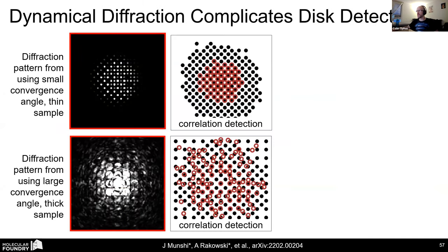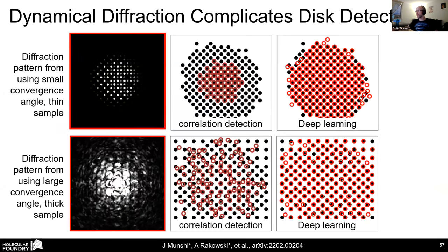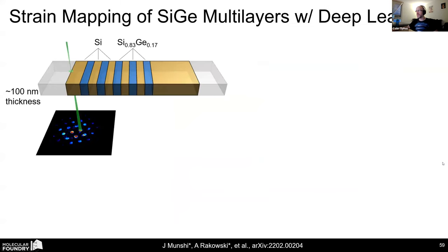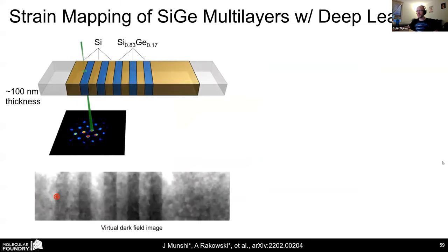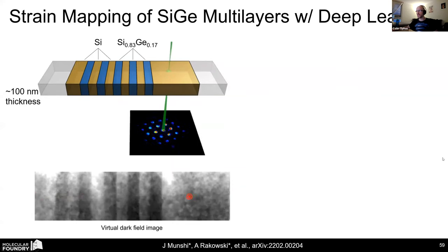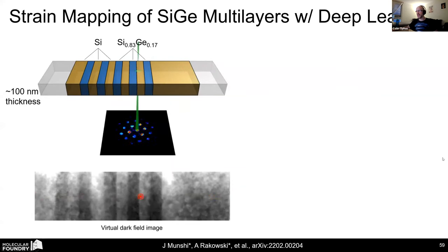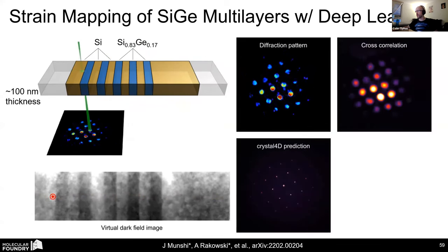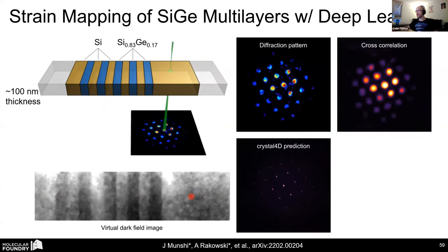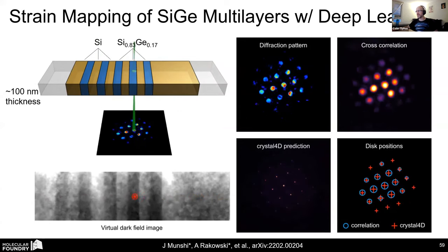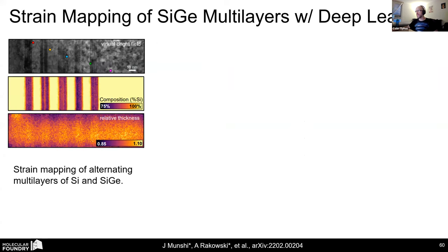And so if I return to those two simulated examples, you can see that the deep learning network just has no problem whatsoever. And a part of this is because it has seen every single crystal structure that is known essentially from these databases. So we can encode a huge amount of prior knowledge into these networks. So I'll show you one experimental example, 100 nanometers thick of silicon and silicon germanium multilayer stack. And if we do our 4D STEM scan, and then we use correlation or the machine learning method to measure the displacements here, and then calculate a strain map and compare them, this is the result.